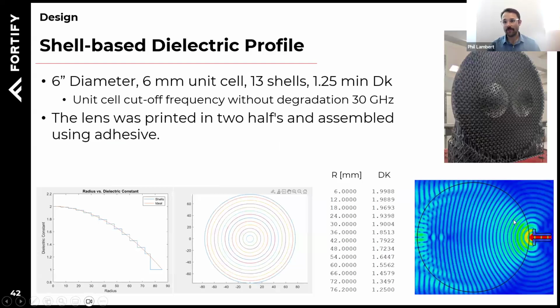Okay, so there are a few ways that dielectric information can come to Fortify. One is a shell-based dielectric profile, and so instead of taking full advantage of arbitrary tailored dielectrics, you can stick with more traditional shell-based dielectrics. They tend to be a little bit easier to design and simulate. And so in this case, what we're looking at is a stepped design. So we've got the shells distribution with 13 shells with a dielectric constant minimum of 1.25, and you can see that here. And you can see how this shell-based distribution overlaps with more of a pure Luneburg style distribution. This lens was printed in 2 halves and assembled.